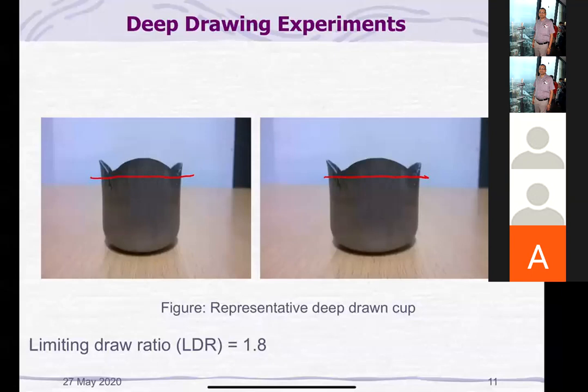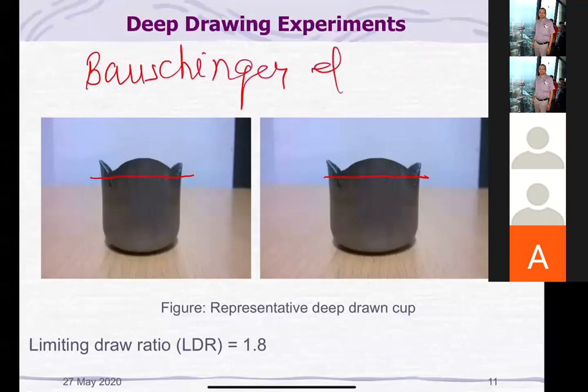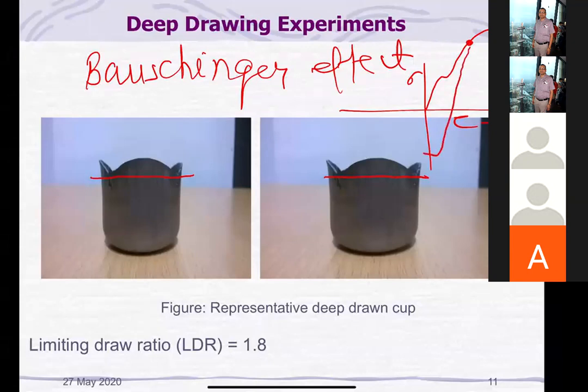But up to 400 degrees centigrade, titanium exhibits a very strong Bauschinger effect. This Bauschinger effect, some of you may know that. Let us briefly explain this here. Once again, a stress strain diagram. This is the tension. Suppose you have loaded the specimen up to the work hardening region. When we unload it and load in compression, the yield point in compression will appear prematurely.